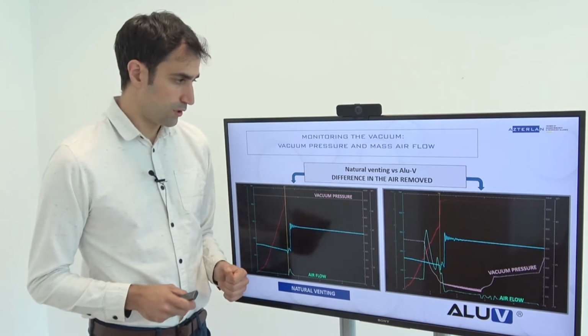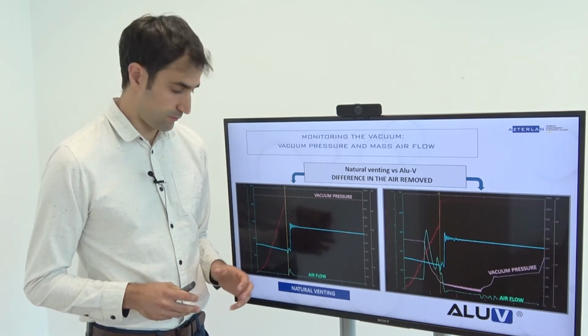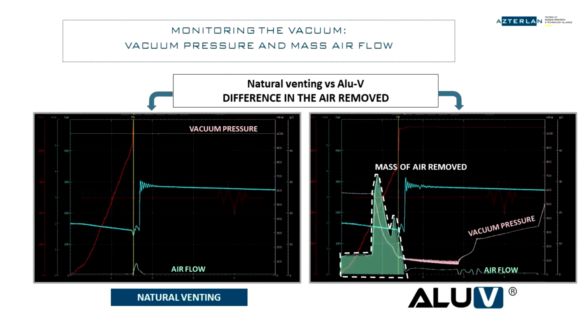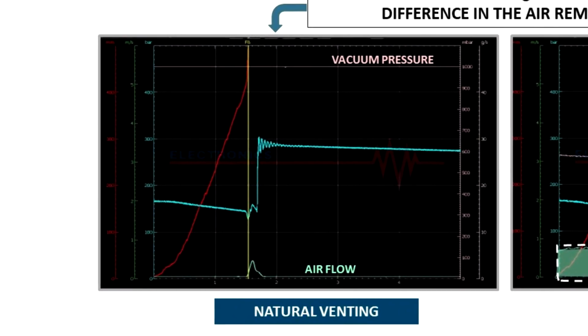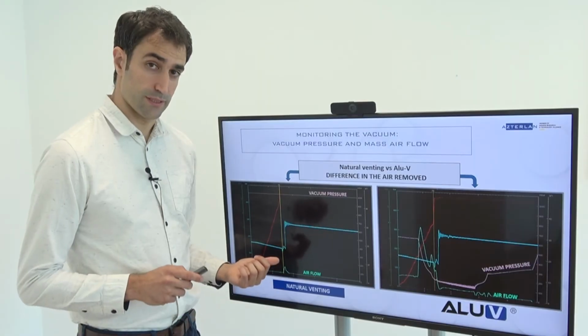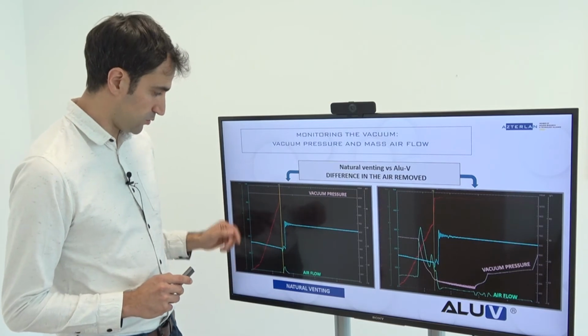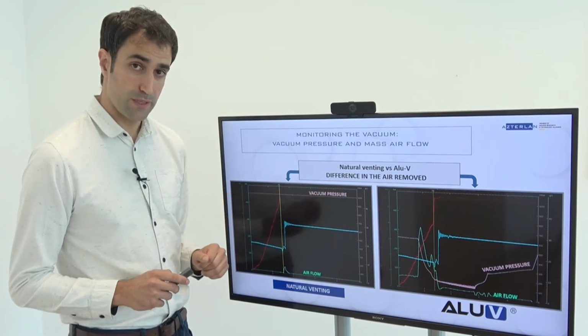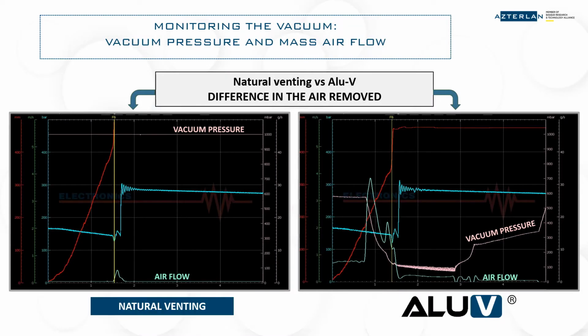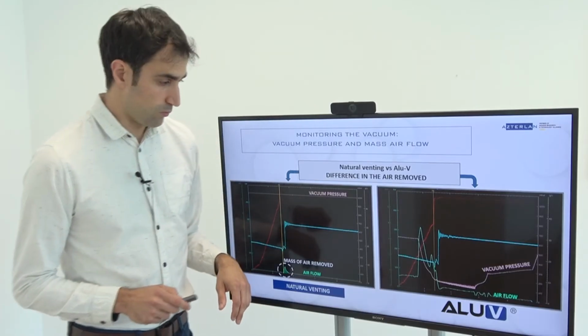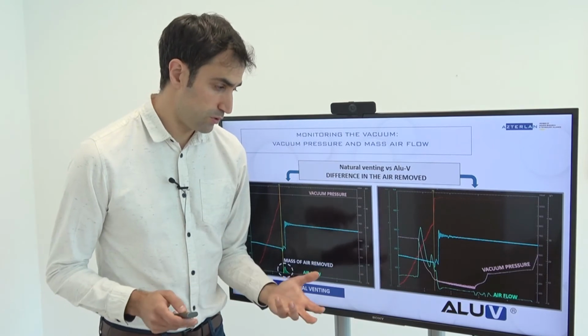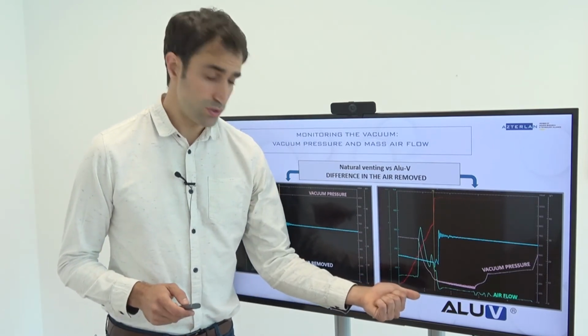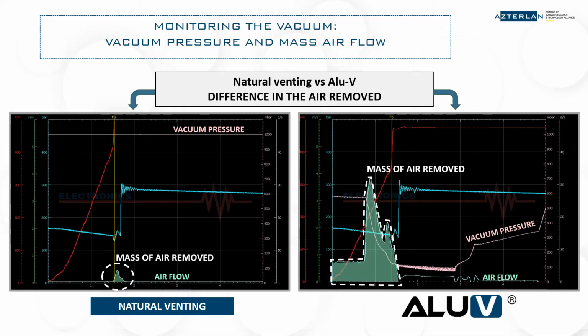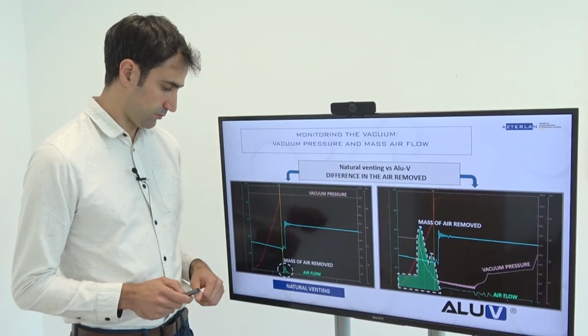Now I would like to look at the monitoring of airflow and the difference between the natural venting and the use of ALU-V. So in this injection curve that corresponds to a mold including the vacuum system, but in which the ALU-V was not activated, as a result we record no vacuum pressure, but there is still an airflow measurement recorded. This corresponds to the mass of air removed through the natural venting. Whereas, in this injection curve that corresponds to the same mold, but on this occasion the ALU-V was activated, we recorded a higher amount of airflow that corresponds to the difference between the mass of air removed through the vacuum compared to the natural venting.